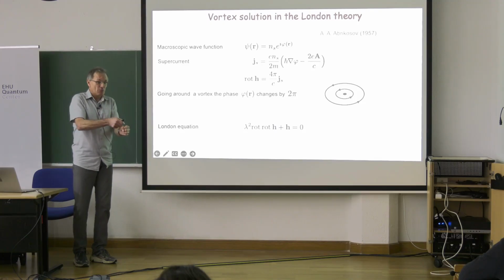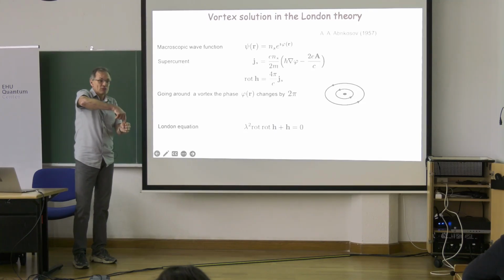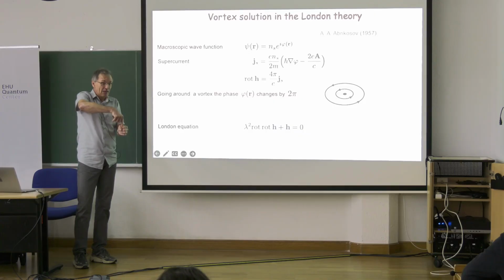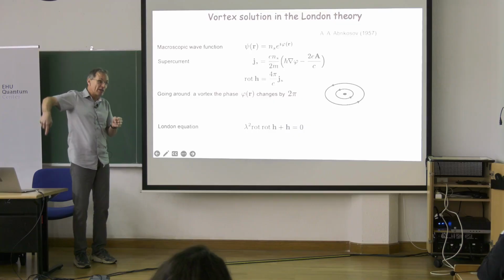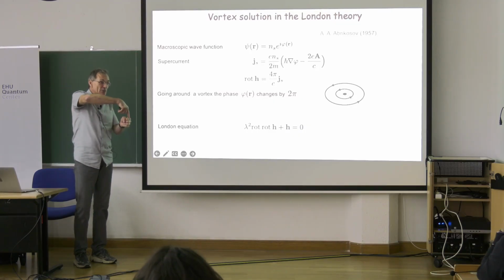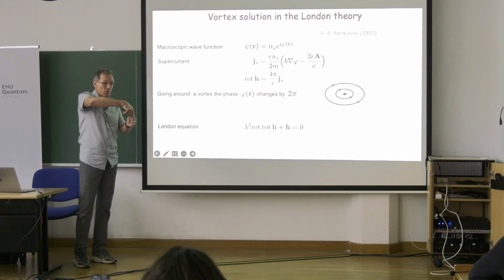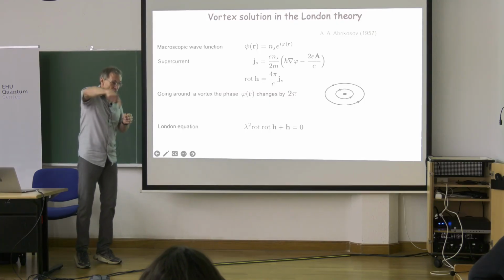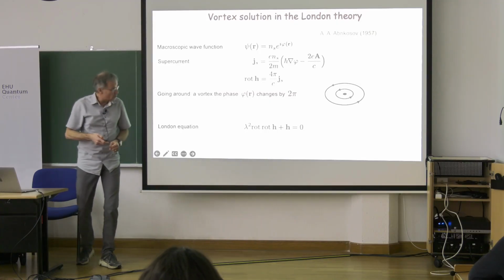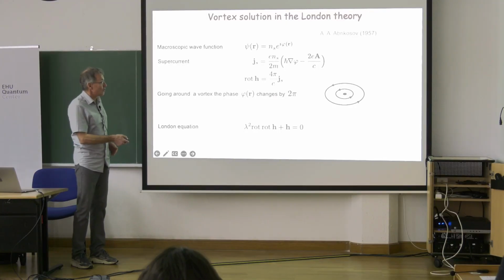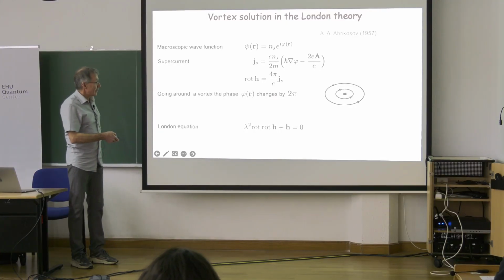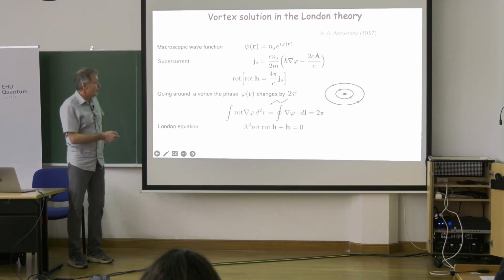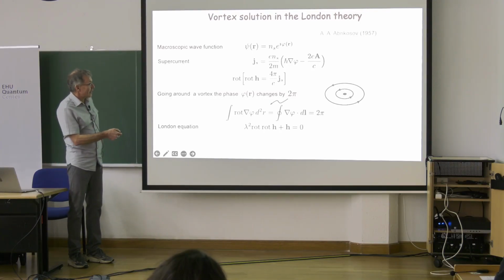Because at this point we go around, we come to the same point, here we have the same psi. But the same psi doesn't mean the same phase. When it goes around, the phase can change by an integer number of 2 pi, and we still get the same wave function. So in the simplest case, it would be just 2 pi. Then if it's 2 pi, when we take the rotation of this gradient, it would not be 0.